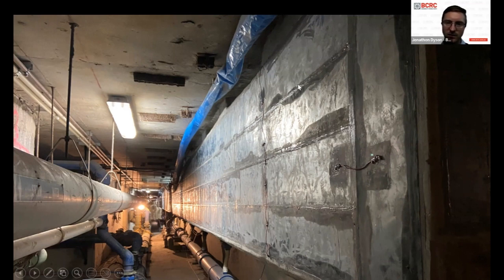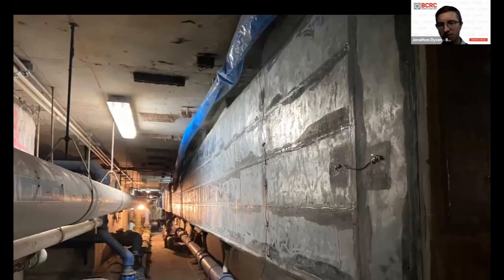What I want to point out about this one here is that you might have noticed that in the previous slide, there was some spacing between the zinc layer anode strips. And that was because that was how it was designed. That amount of zinc anode was needed to provide that cathodic protection for the amount of steel reinforcement in that slab. In this case, the side of the pool walls had so much reinforcement in them that our design demonstrated that we actually needed to have 100% coverage of zinc layer anode. And also the zinc layer anode needed to be twice as thick in order to achieve the cathodic protection for the given design life extension.